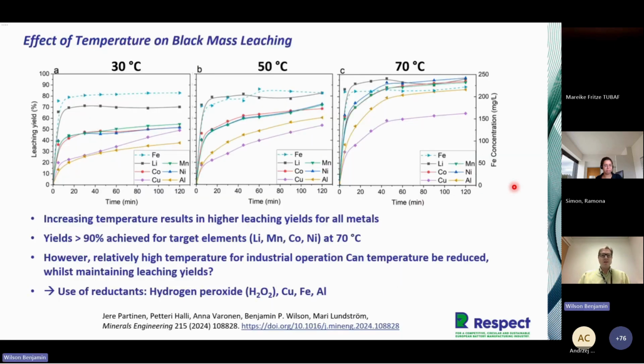The first thing that we looked at was the effect of temperature on the black mass leaching. This is without any reductive agents added. This is just looking at temperature and the sulfuric acid lixiviant. As you can see here, as the temperature increases, not surprisingly, you start to see higher yields of the critical metals, particularly manganese, nickel and cobalt. So yes, temperature has an effect. And at 70 degrees, we found yields above 90% for the target metals.